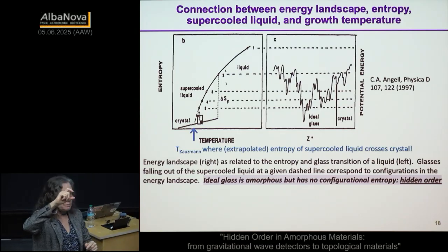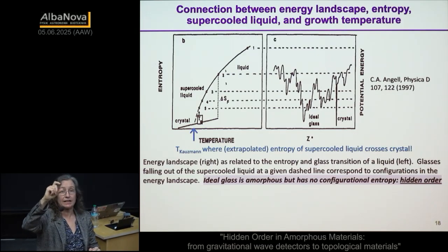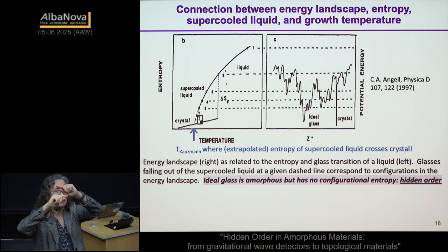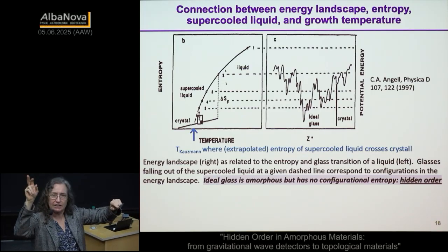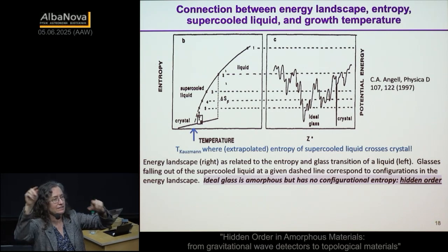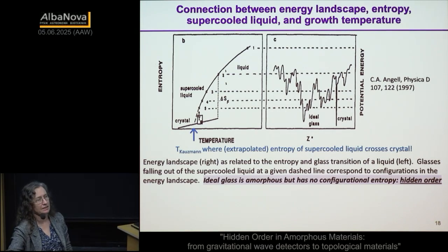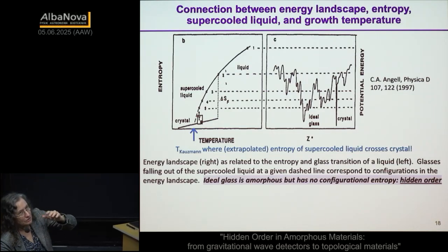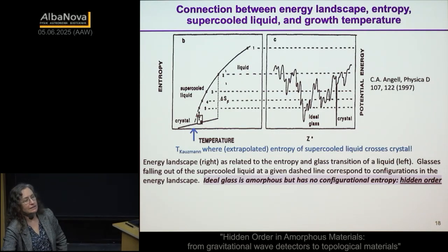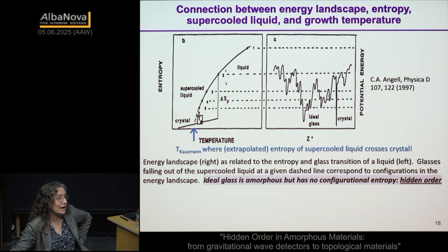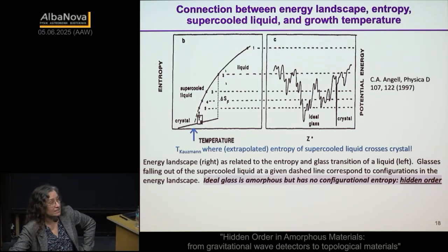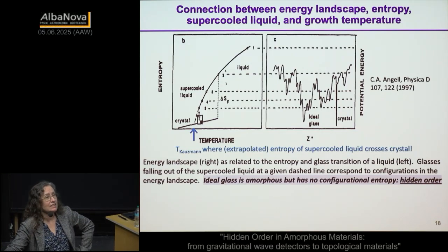There's only a tiny bit of energy lost even at the crystallization. So the heat capacity is not that much higher in the liquid state than the crystalline state. So the extrapolation takes TK down to 2 Kelvin or something like that. So my underlying hope is that this is all about TK. And how do you get TK? Again, that's a liquid phase property, not anything to do with glass freezing. It's about the difference in heat capacity in the liquid compared to the crystal, both of which can get measured.